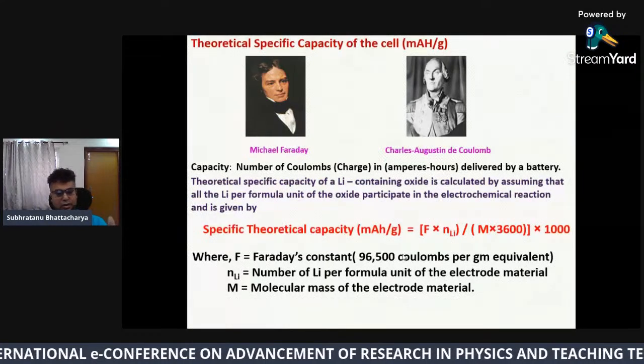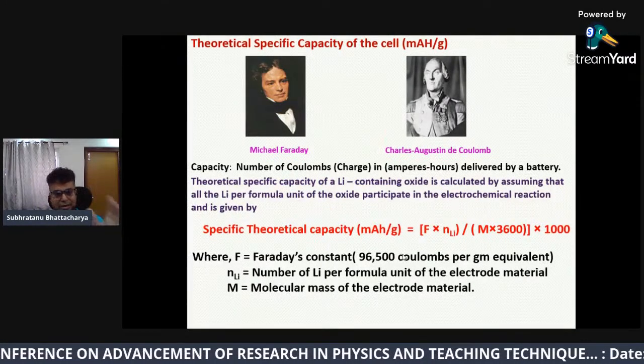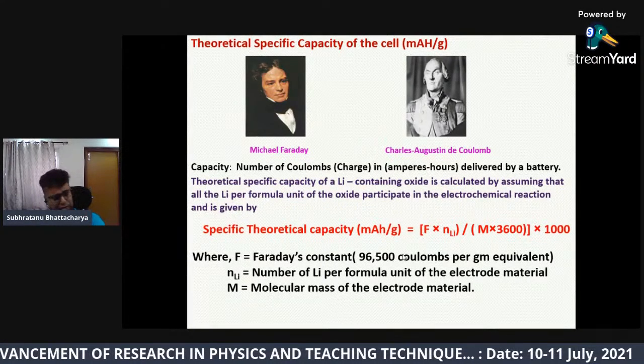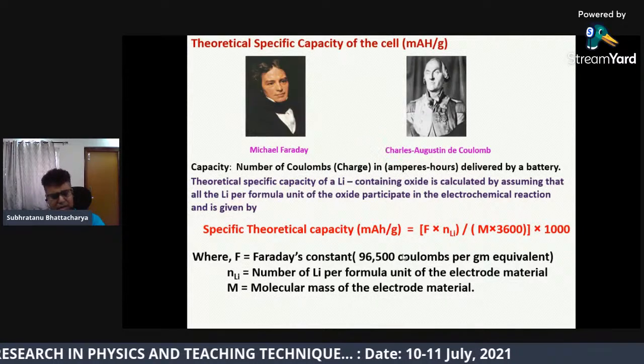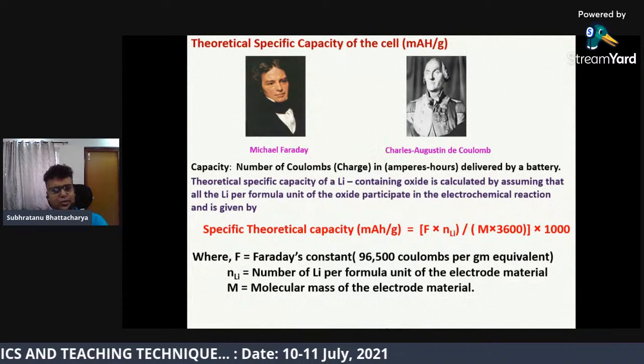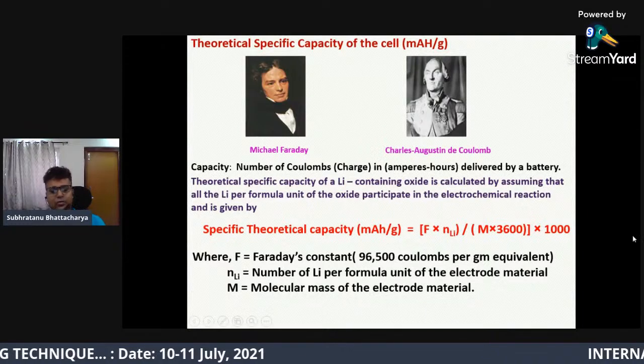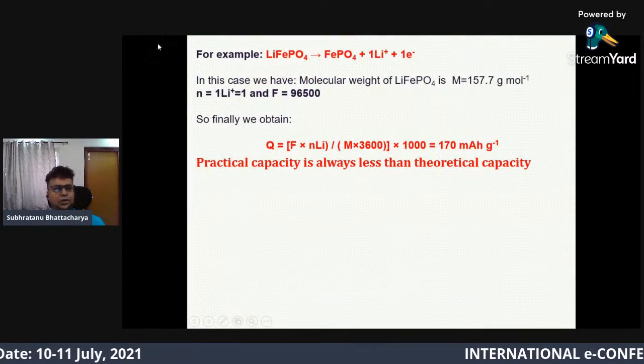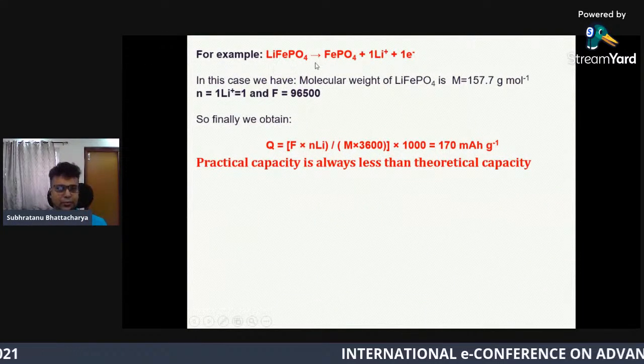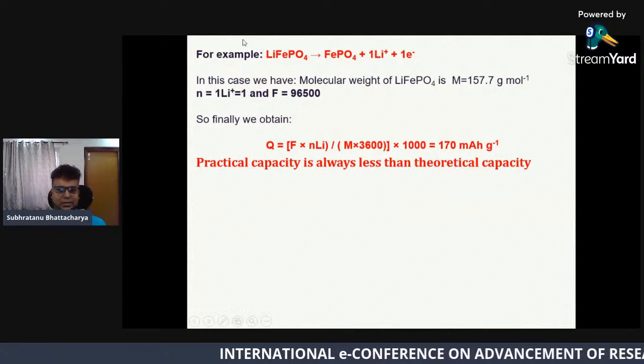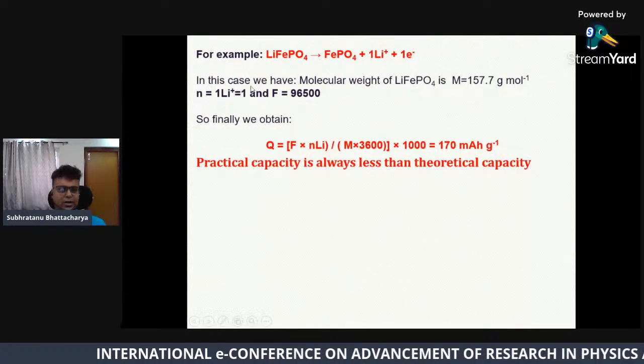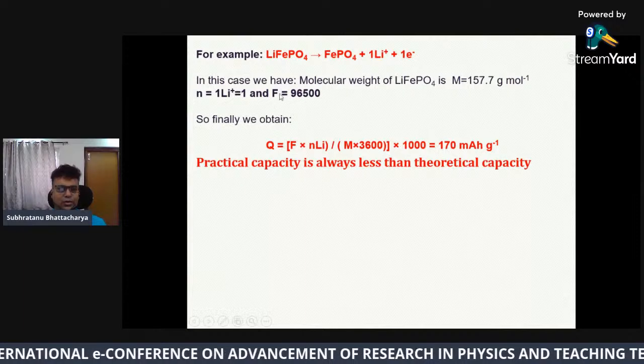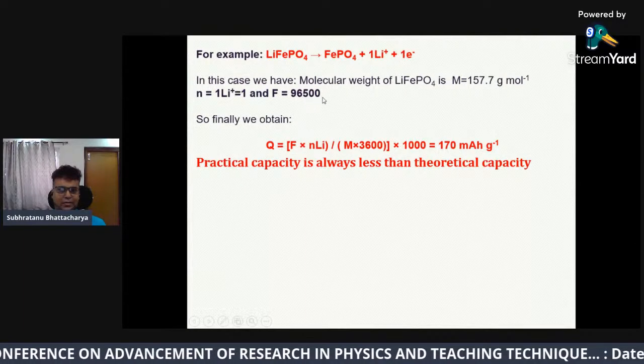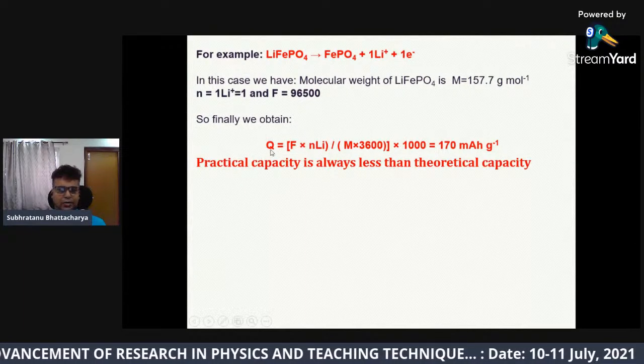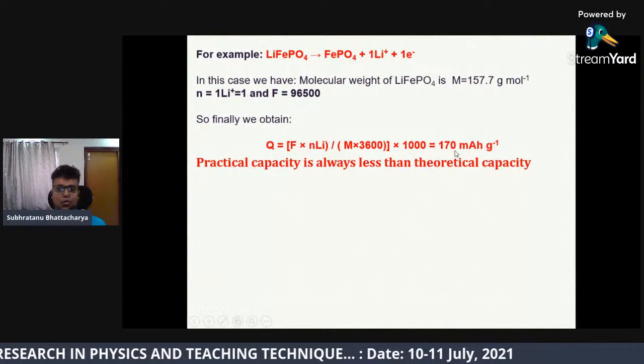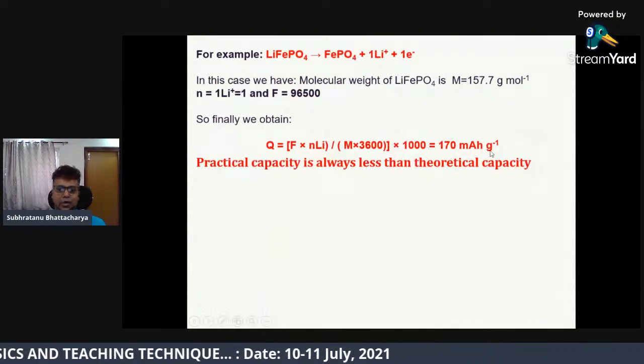Like I told you, if you consider 100 lithium ions coming from one cathode material, this 100 lithium ions means how much capacity? That will be the theoretical capacity. For example, LiFePO4, this is the electrochemical discharge reaction. If the Faraday constant is 96500, finally you can obtain the theoretical capacity as 170 mAh per gram.